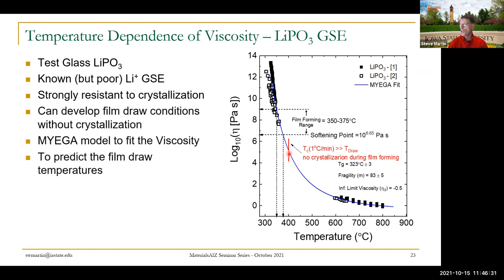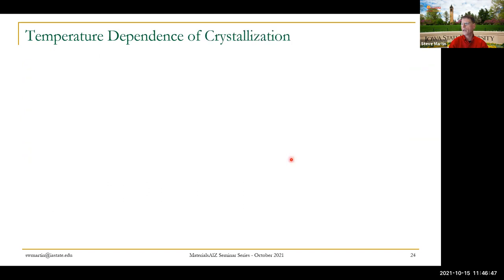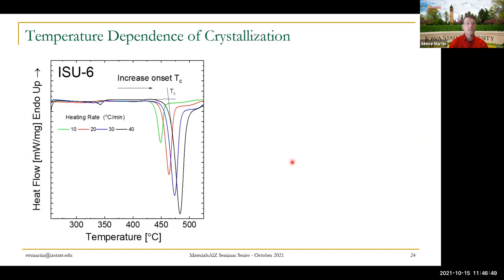After we know what the viscosity is, of course, we don't want the liquid to crystallize in the working range. We want it to crystallize well above that. So we have to figure out what the crystallization temperature is. We do a series of heating rate studies in the DSC. This happens to be ISU6, apologize for that. That's the LiPO3 composition that I talked about.